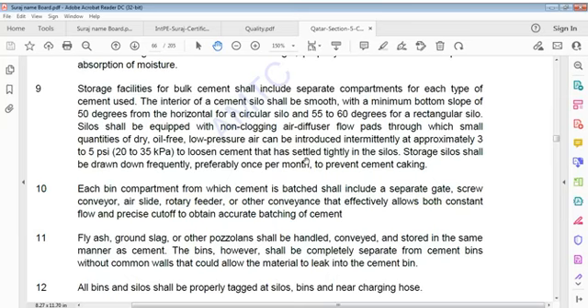Non-clogging air diffusers are flow pads through which small quantities of dry, oil-free, low-pressure air can be introduced intermittently at approximately 3 to 5 psi or 20 to 35 kPa to loosen cement that has settled tightly in silos. Storage silos shall be drawn down frequently, preferably once per month, to prevent cement caking.